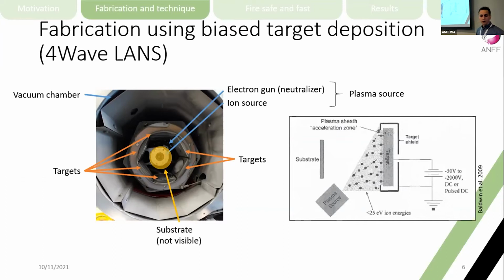Now in 4-wave, we typically apply this voltage as a pulsed DC voltage, and because in 4-wave we can control up to 4 targets at the same time, we can apply this pulsed DC voltage to up to 4 targets at the same time, and we can control the bias strength and the pulse duration. We can fabricate any arbitrary alloy with up to 4 constituents.